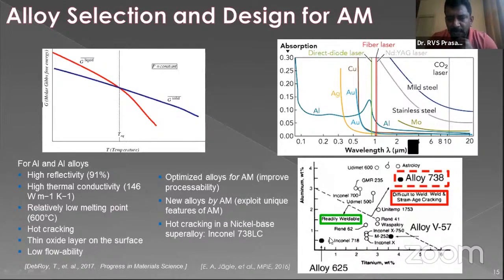At the same time, even if you see the following diagram for Inconel based alloys, for example, the aluminum and titanium percentage in that particular alloy will play a significant role. When the aluminum and titanium content is lower, the weldability of these particular alloys like IN718 will be very good. However, when you are going for, in the same category of nickel-based super alloys, something like IN738, then it's very difficult to weld, because the percentage of aluminum and titanium will vary and the weldability is also going to differ. So in a way, this kind of alloy diagram and processing maps will give a clear picture of how to select an alloy for these 3D printing processes.